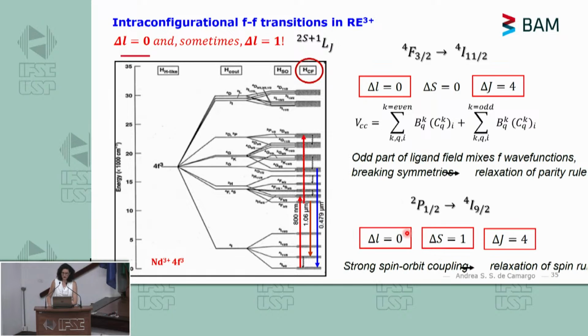Now let's look at another transition of neodymium. This one is in the blue here at 480 nanometers. This one has delta L 0, delta S 1, so again violating the spin rule, and delta J equals 4. And now you ask yourself, what is the reason why the spin rule is relaxed in this case? The reason being there's a strong spin orbit coupling. So when there is a strong interaction between spin and angular momentum, then these numbers are not good anymore. They're not pure, they're mixed, and then you have selection rule relaxation.